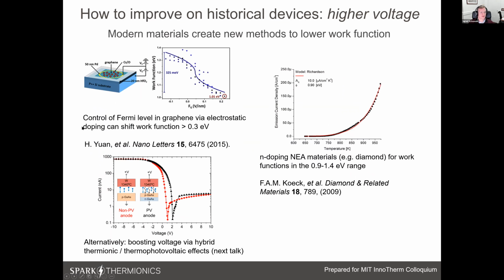There are a few schemes in literature in order to use conventional coatings, but then shift the Fermi level within the device, such as here with backgating in a graphene collector. And while it shares some differences, and you'll hear more about it in the following, I also look at techniques to combine thermophotovoltaics and thermionics as part of this Fermi level splitting and shifting, because at the end of the day, it's all towards increasing voltage. But there are other techniques as well. There is a lot of work that has been demonstrated in diamond, for instance, that gets work functions within this low level. But I will mention that these will be limited currently to fairly low current densities, and that should be an active area of research to overcome.